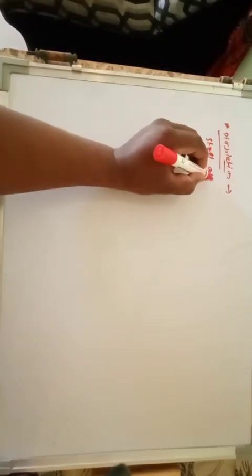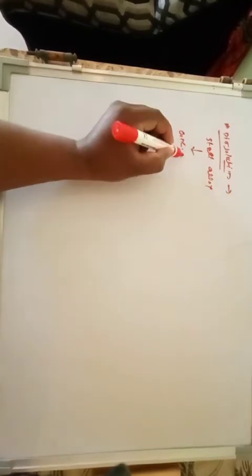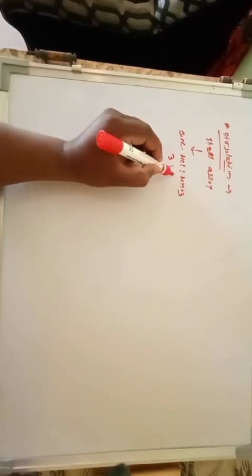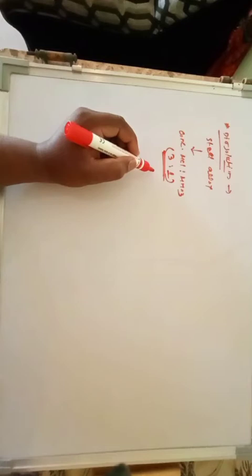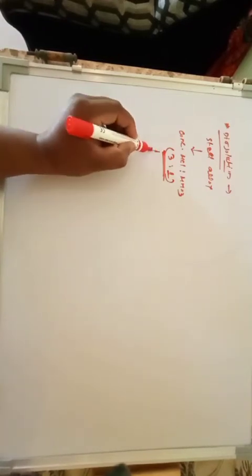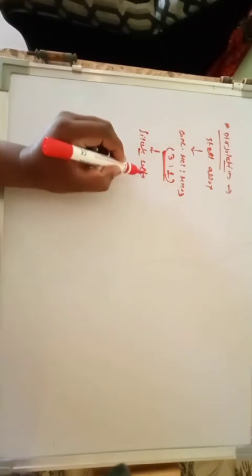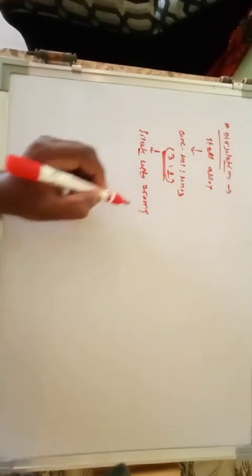So let us discuss the dissolution procedure. You have to weigh the steel alloy and dissolve it in concentrated HCl and HNO3, that is in 3:1 ratio. It is an aqua regia mixture. After dissolution you have to dilute up to a suitable volume, that is, dilute up to 250 ml. Let us consider 250 ml.